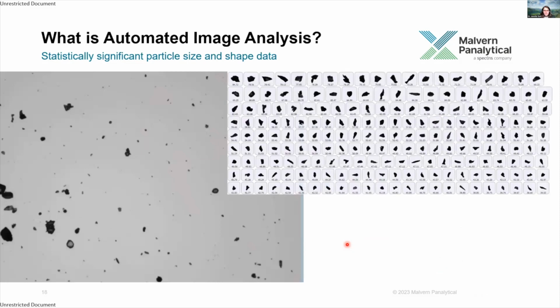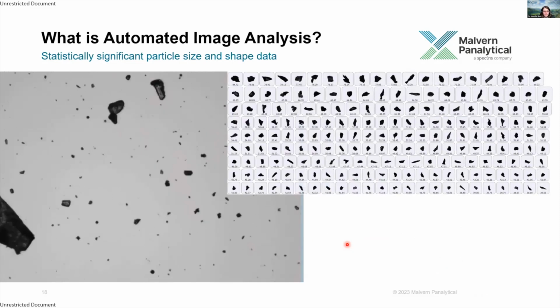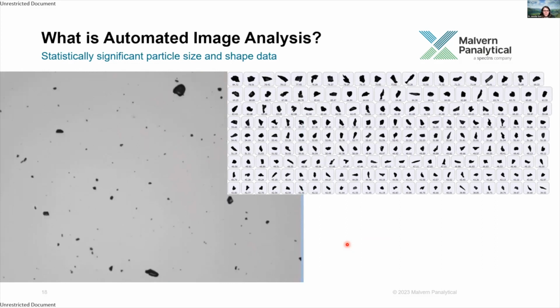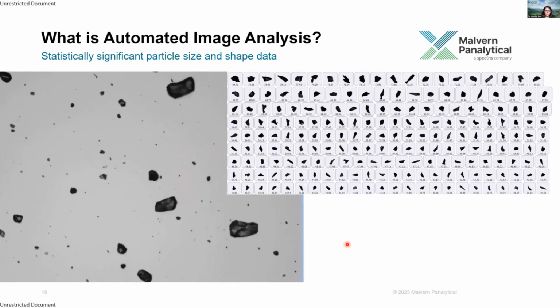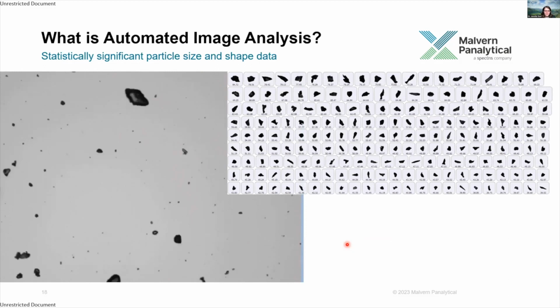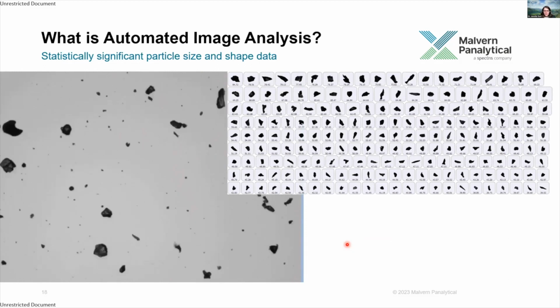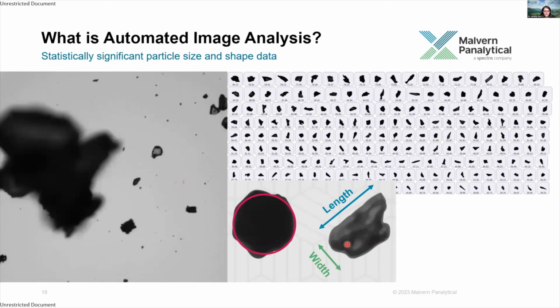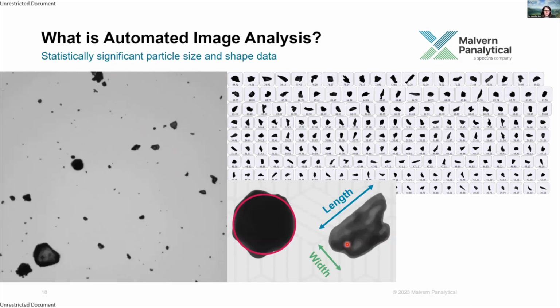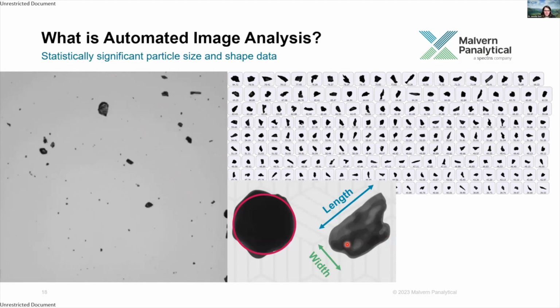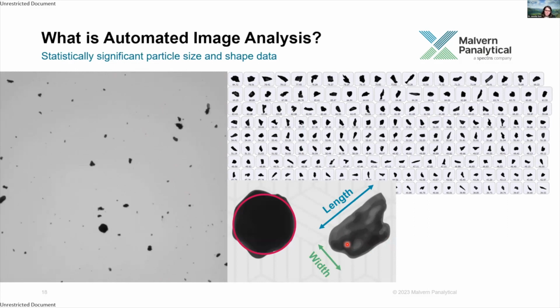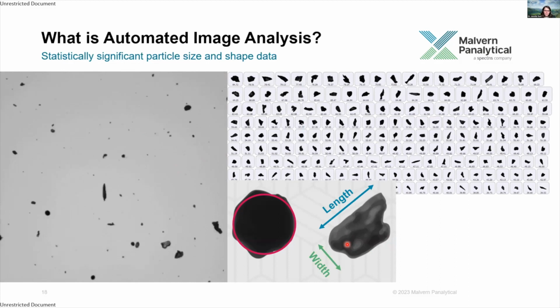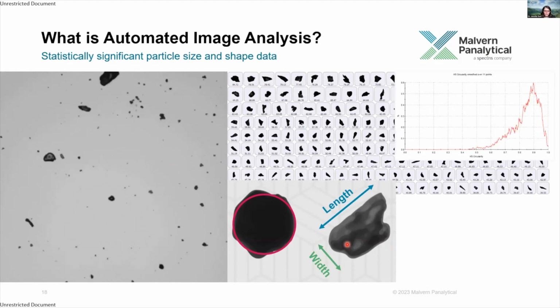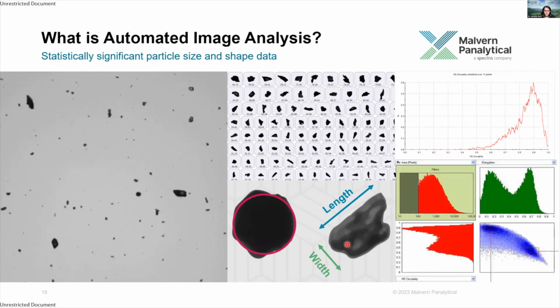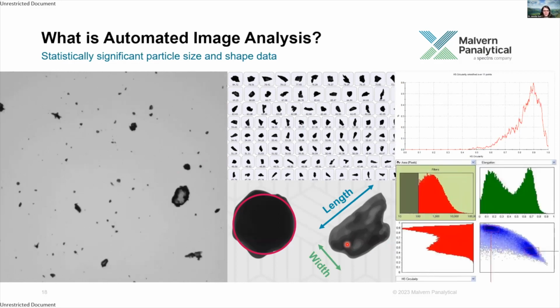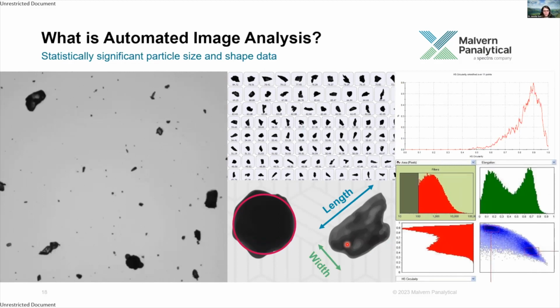Well, in automated image analysis, we automate the capture of images of dispersed particles. So we'll take images of hundreds of thousands of frames, and from this you'll get tens of thousands of individual particle images. From these images, we can extract size and shape data, so things like the circular equivalent diameter, length, width, circularity, elongation, convexity, and we have that for each individual particle. But then we can also build particle size and shape distributions and use the tools within the software, such as scattergrams and comparison tabs, to compare these distributions and to produce results.